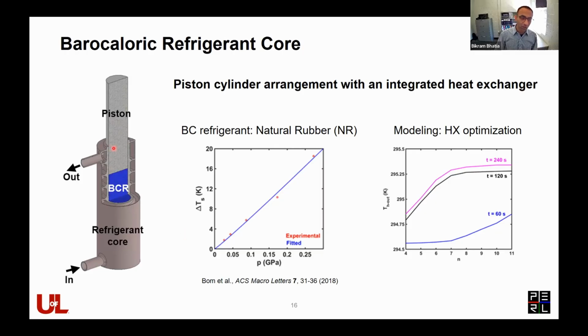So we did that using a helical heat exchanger that surrounded this barocaloric core. And we modeled the transient heat transfer from the barocaloric core when we apply pressure and how that pressure gets transmitted to the heat transfer medium around it, which in our case was ethylene glycol. And we looked at, okay, how does the temperature evolve over time as a function of different number of passes of the helical heat exchanger.